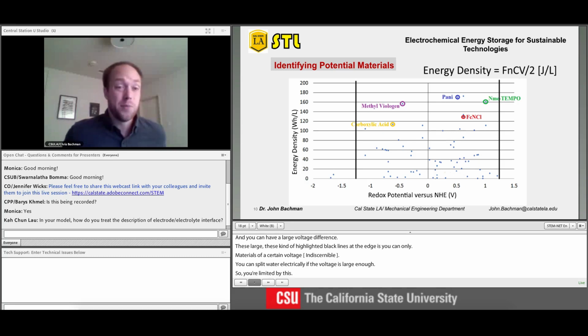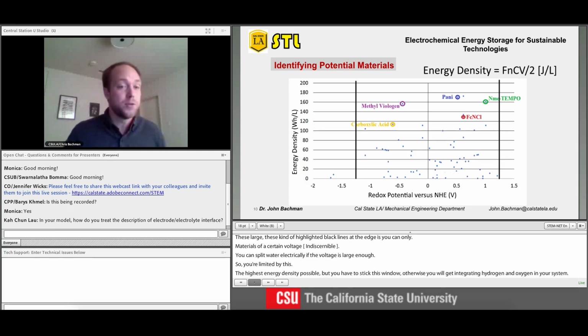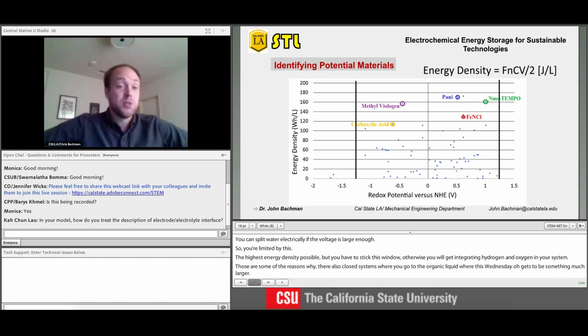And that's part of the reason why there are also proposed systems where you go to an organic liquid, where this window gets to be 4 volts or something much larger. So my students did a thorough review of the materials, picked out some of the highest potential materials in this landscape, and we're now at the process to begin to screen some of these materials in this actual system.